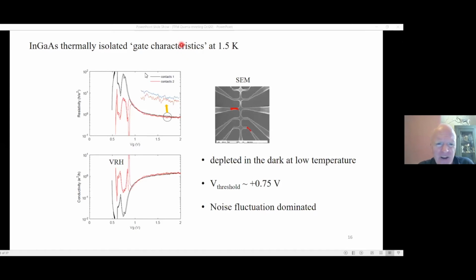This is what the gating characteristics look like. So I'm plotting resistivity now as a function of gate voltage. This is that same device under the SEM. You can see I've put red areas here. And I think what happens is these red areas deplete first. You can even see some breaks in the device here. So this is the gate characteristic. This is gate voltage. So if we start from 0 gate voltage, they are completely depleted. They don't conduct at all. Putting a positive gate voltage on, the device starts to conduct. We start to get the contacts back, and the device starts to behave in a reasonable way that we can change the carrier density from the gate.